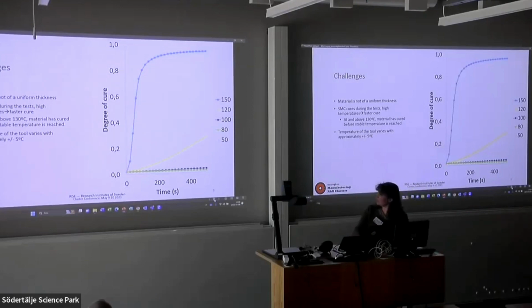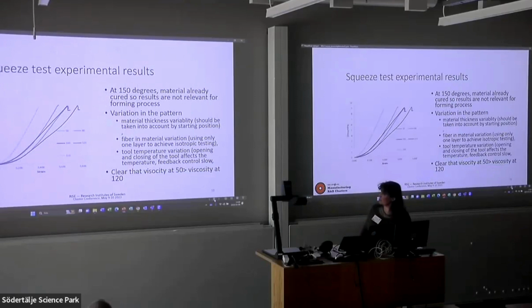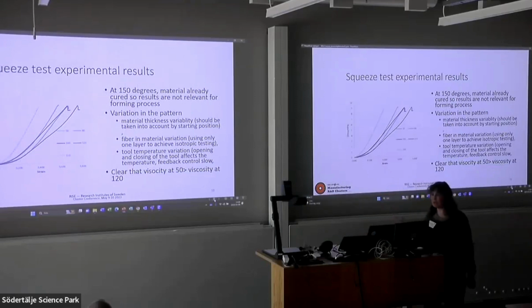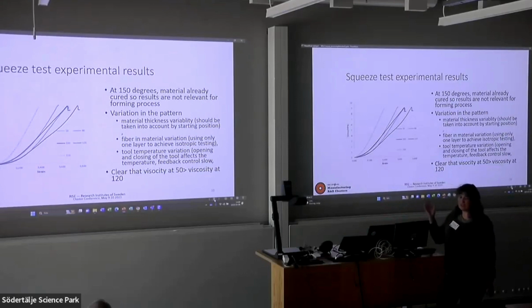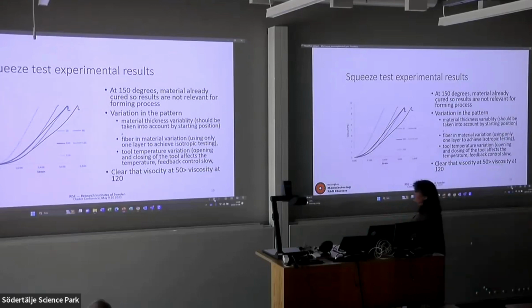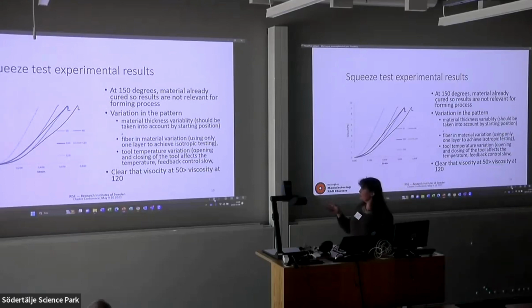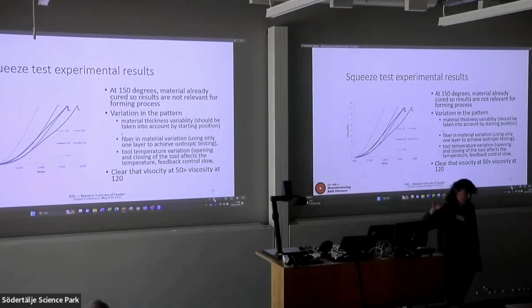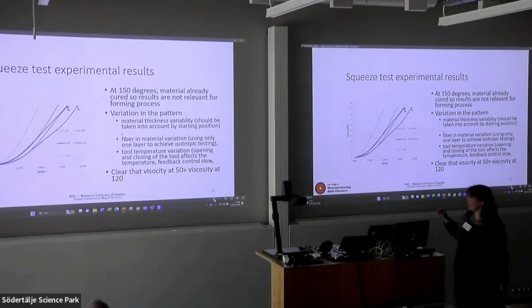So we end up with, we can get how it behaves at high temperatures and how it behaves at low temperatures, but the in-between is affected by these other factors varying in material, the differences in the tool temperature. What we found is better is to model from one to the other, to be able to get a consistent behavior, a linear behavior, a modelable behavior.